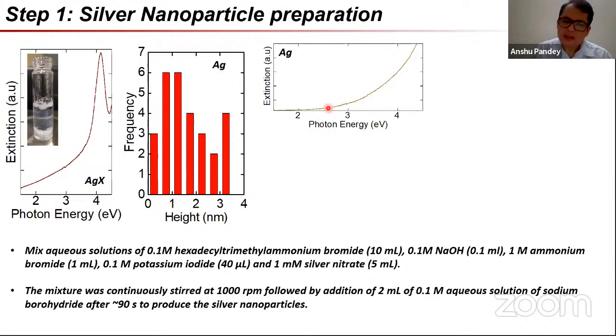The silver particles we are making, which is critical, lack a plasmon resonance. They are too small to have a proper well-defined plasmon resonance. This is how their extinction spectrum looks if you make them. This mixture is stirred, and following that, these are of course all taken after adding the sodium borohydride.